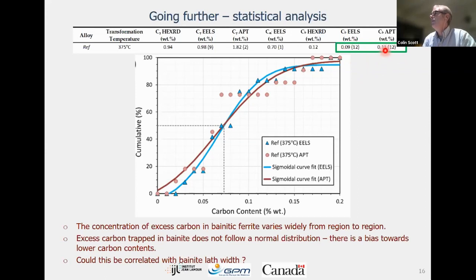They agree pretty well. But if we do a statistical analysis where we divide those data up into, I think it was 0.05 weight percent blocks and plot the cumulative graph, then we get these two distributions. So the blue triangles, that's the yields distribution, and the red is from the atom probe data. They do follow a sigmoidal type of distribution. But when you look at the 50%, the median value, you get something about 0.07 weight percent carbon in bainitic ferrite, which is smaller than both of these and significantly smaller than the APT.